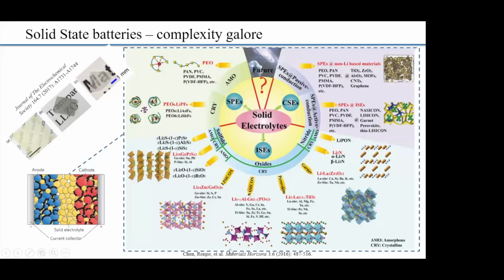And the reference is here. People can go to this paper and read more about it. Basically, sulfides comprise lithium, germanium, phosphorus, sulfide. It's called LGPS in the community. And then you have LISICON, which is lithium, zinc, germanium oxide. It's lithium, aluminum, germanium, phosphate. And perovskites. These are all crystalline oxides.